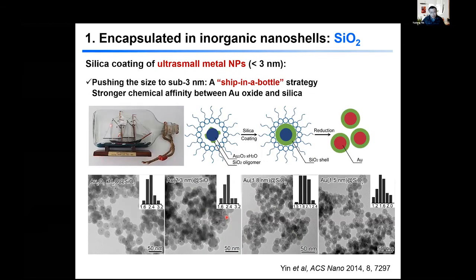My group also extended this process to even smaller particles and with better control. What we did was, instead of creating nanoparticles directly, we create precursors to nanoparticles, for example, in this case, gold oxide nanocrystals by a precipitation reaction. This oxide has very good compatibility with silica, and we can coat the silica with very small thickness. Then after a reduction reaction, we convert this oxide into metal. Because we get rid of oxygen in this case, the particle can actually get even smaller. So by using this method, we can produce very small particles, 1.5, 1.8, 2.3 nanometers, with very good control and very good encapsulation in the silica.